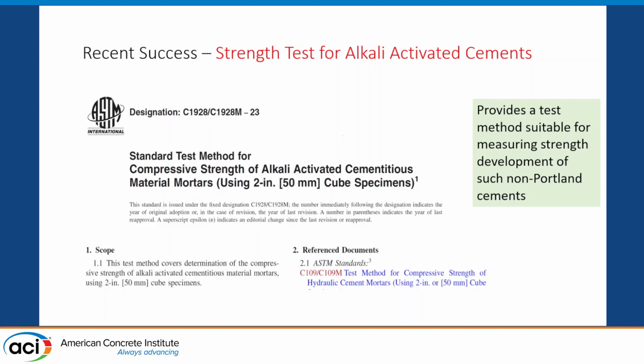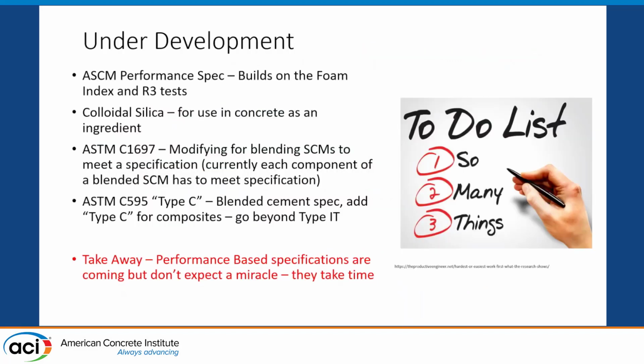There's a test that just came out this year on strength of alkali-activated cementitious systems. Again, for the cement side, basically using the same 2-inch cubes that people use for other acceptance tests, but it's been modified to allow them to test these alkali-activated systems. There's a lot of things that still need to be done.